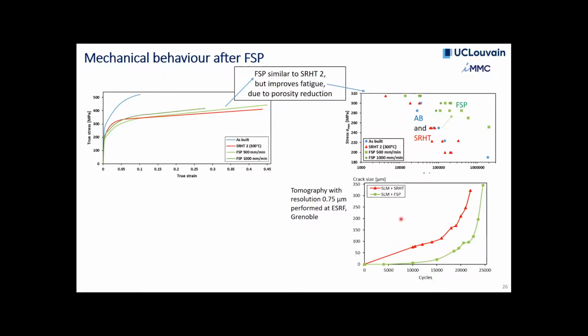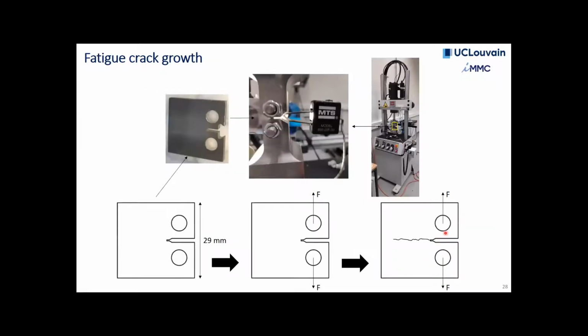These are conditions of low cycle fatigue due to the constraints of the synchrotron. But what you see here is that it grows pretty much at the same speed. So we wanted to have a look at that, and so we did fatigue crack growth conditions here. And so these are standardized tests where we look at the fatigue crack.